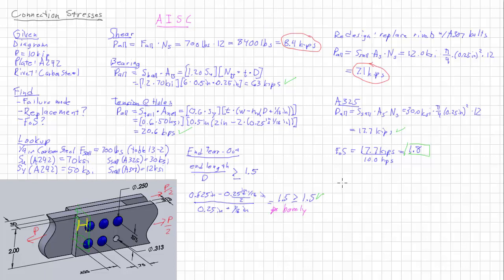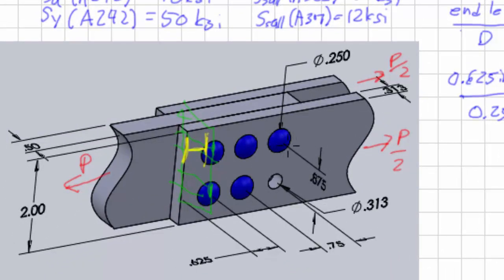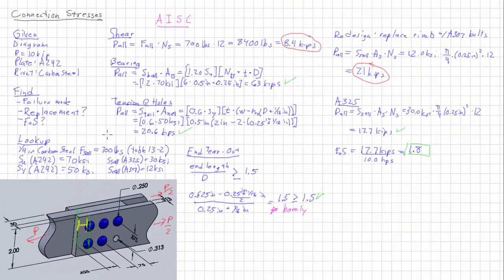Okay, so for this problem, we went over what types of stresses, how they impact a connection, how any one of them can be a source of failure. So you need to calculate all of them to compare and see what's going to fail. The other thing is that you might want it to fail in one way rather than another. For example, if you designed it to fail in shear of the rivets, you might notice that ahead of time if you compared to failure of the bulk material. And you'd want that so that you could have some warning. So we found the failure mode by doing all those calculations for the shear, the bearing, the tension at the hole, and the end tear out. We found that our design held up fairly well, except for the shear of the rivets.